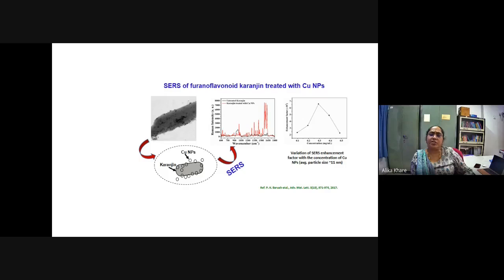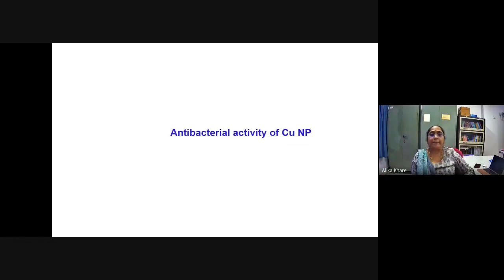Again, optimization is required here, with particle size and particle concentration. If the concentration of copper or silver nanoparticles is very low, the signal will be low. But if it becomes extremely high, the whole crystal gets coated with these particles, and the laser radiation while recording the Raman is not penetrating inside, so the signal falls down. So some optimization is required in these cases.